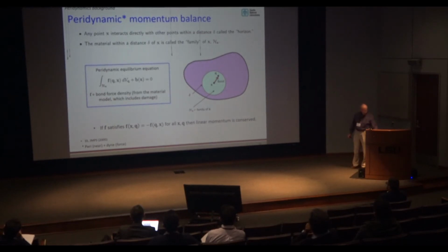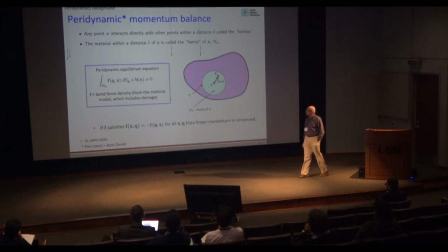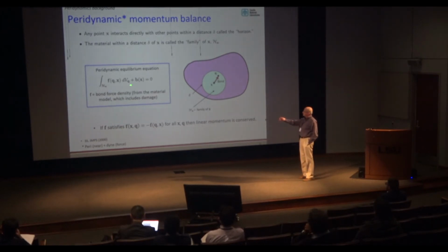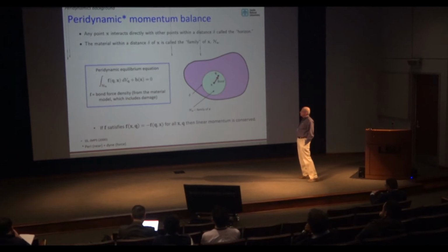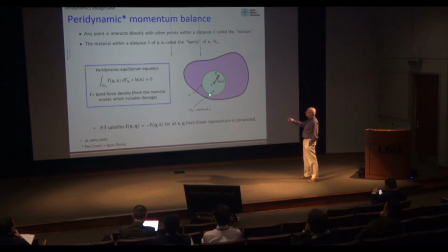What the peridynamic equations look like are basically, this is the equilibrium equation. So instead of the divergence of the stress tensor field, we have this term that sums up force interactions across bonds from x to q of finite length. There is a cutoff distance for these interactions called the horizon, delta, and everything within the distance delta from x is called the family of x. F is provided by a material model which looks at the deformation of the family and comes up with values of the bond force densities which appear in this integral.